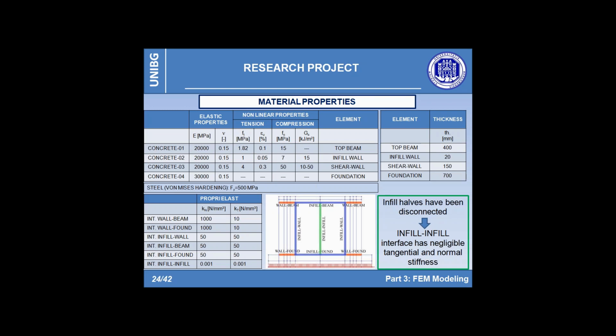Moreover, interface elements have been implemented along the entire perimeter of the infill so as to reproduce the limited degree of cohesion with the outer frame. In this case, the tangential stiffness has been increased, taking into account that the infill is confined by the external structure, such as the outer frame. Finally, a further elastic interface imposing stiffness values practically equal to 0 has been inserted also in correspondence of the center line of the infill to catch the relative sliding movement between the two halves.